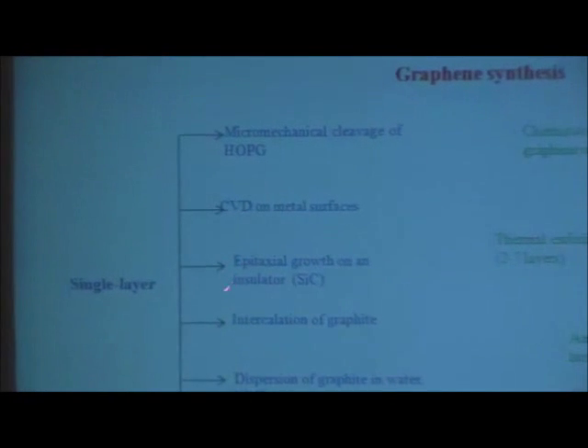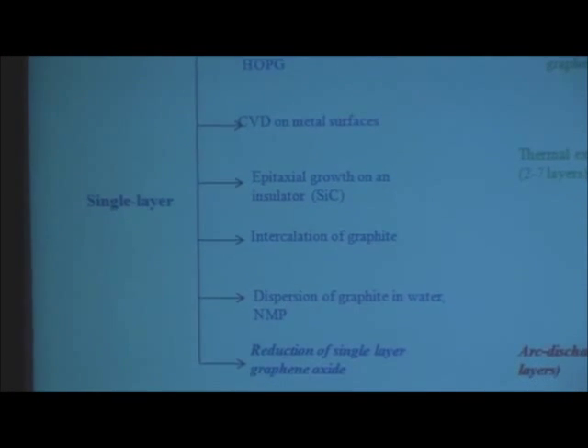Single-layer graphene can be made by mechanical cleavage, I told you about, CVD on metal surfaces. But the trouble with single layer is you can't take it out. It has to be on a substrate. The minute you take single layer, it all becomes graphite again. You can't take it out. So that is the problem. Okay? But recently, I've just added, a day before yesterday, before I came, you know what we found? You take this graphene oxide. There are papers in Science and Nature saying this: take this single layer graphene oxide, reduce it by a vapor of hydrazine or something. Man, who wants vapor of hydrazine in a good engineering or a physics lab or even in a chemistry lab?